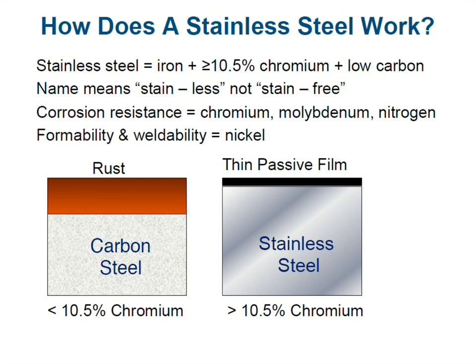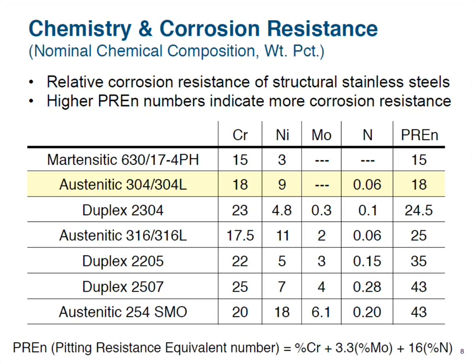There are also inherent differences between stainless steels in corrosion resistance, and you can do a calculation based on the chemistry to determine the relative corrosion resistance. There's a lot more about this on your flash drives, and create a PREN number. That's a pitting resistance equivalent number. I've shown a few stainless steels that are used for structural applications, and you can see the last column is a PREN number. The higher the number, the more corrosion resistant the stainless steel.